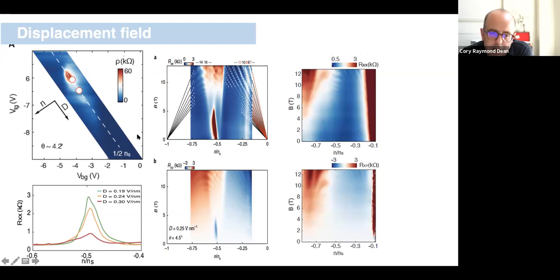In the middle column here, what I'm doing is taking a point in this 2D plot that's in a situation where we have a well-defined gap at half filling. And then on the right, I'm measuring a similar response, but where we've moved off of the resistance peak. So we're still at half filling in these 2 plots on the right, but at a displacement field value where there no longer is clearly a resistive state. So what we see in these 2 plots is the following.